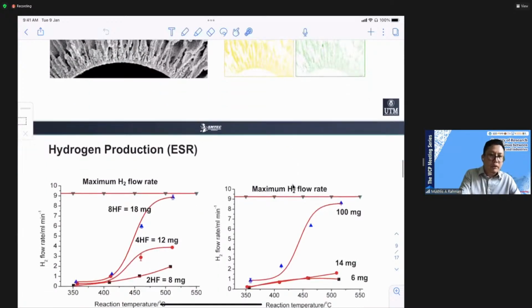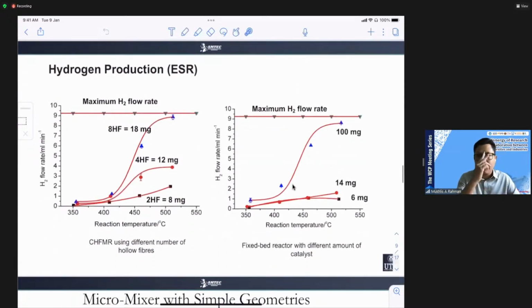Now we want to see the performance of our ceramic hollow fiber membrane in comparison with a fixed bed reactor. This is hydrogen production using ethanol steam reforming. We can see that we stack 2 hollow fibers, 4 hollow fibers, and 8 hollow fibers, so the amount of catalyst increases. If you use 2 hollow fibers, we managed to get 8 milligrams of catalyst. We can see that when we increase the amount of catalyst in the hollow fiber, the hydrogen produced becomes increased.